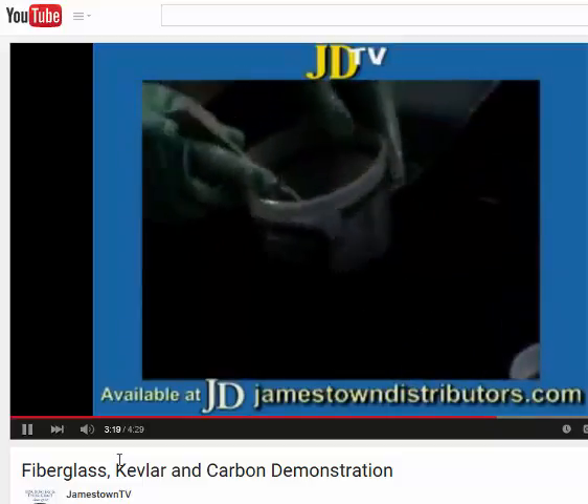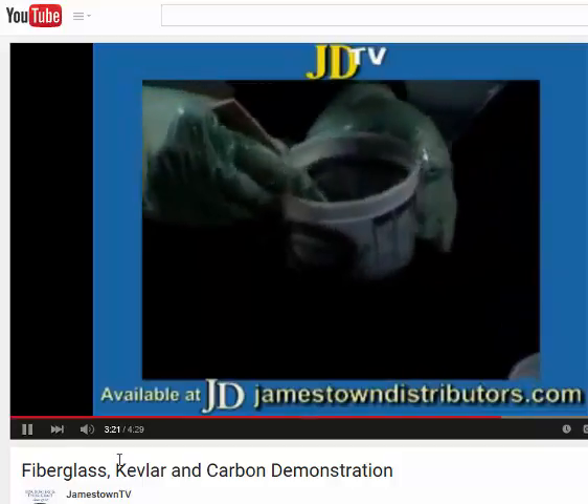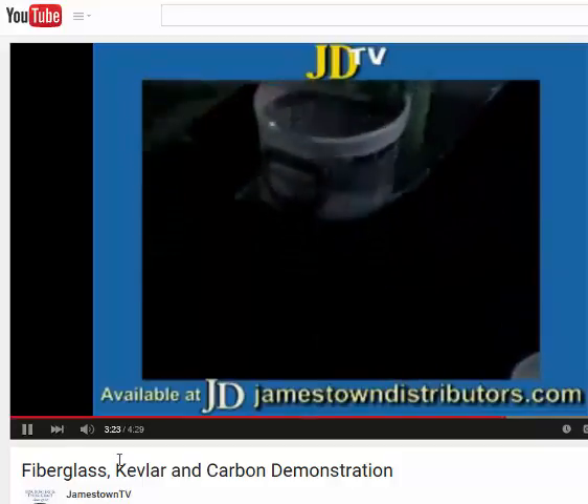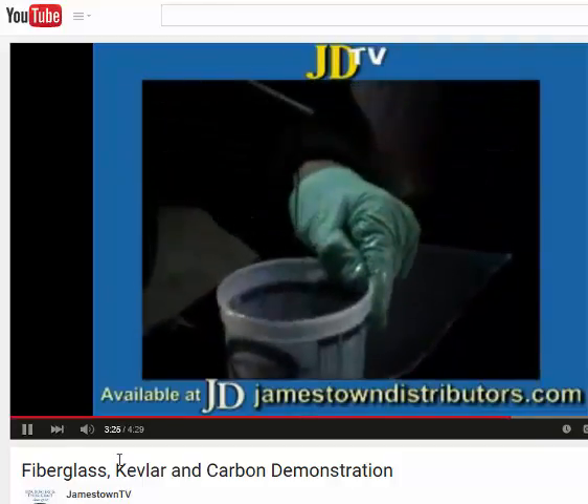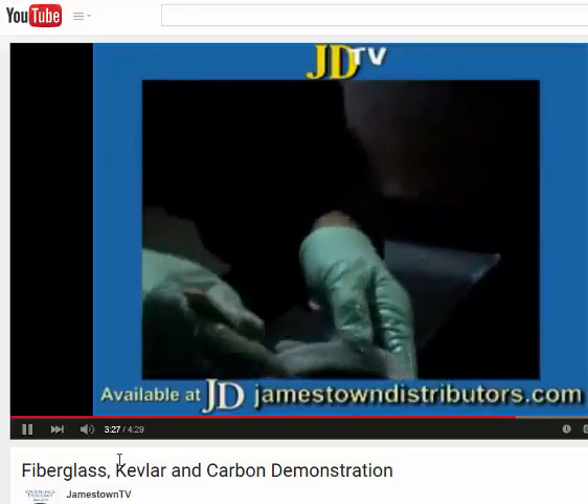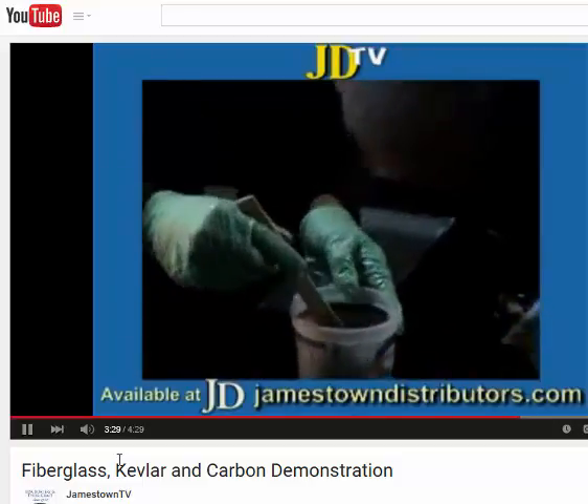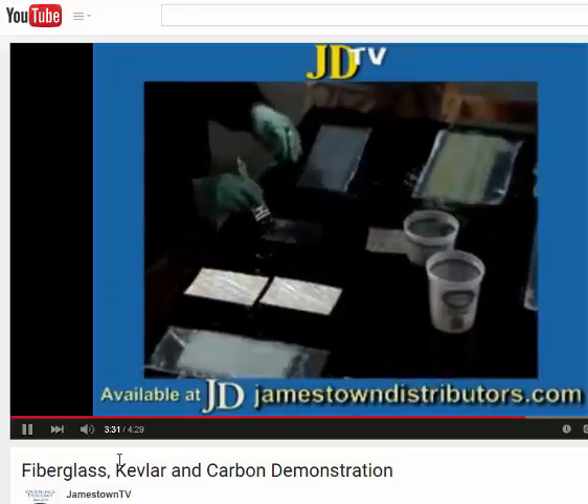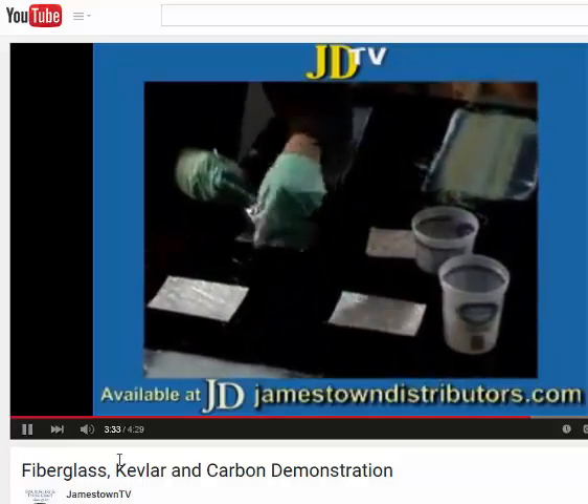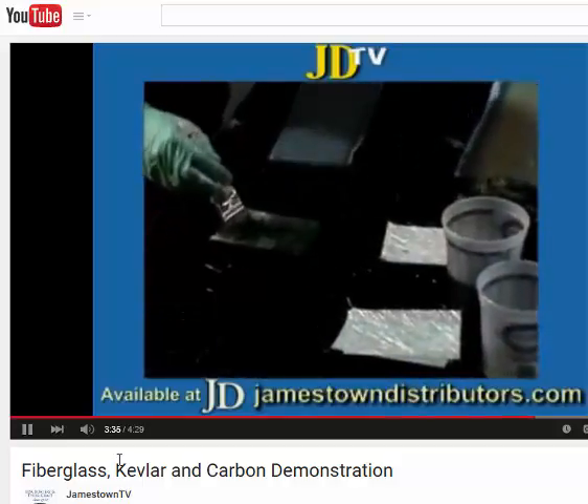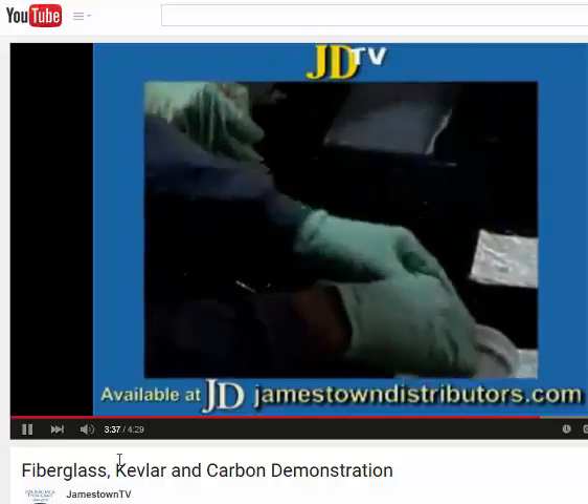This is actually an infusion resin that we have in the shop. It's very, very thin, as you can see, but it's a vinyl ester blend infusion resin. It's a very nice resin. Now, what we could do maybe at the same time is just take the epoxy and do this exact same thing I'm doing with the mat. Just wet that out and then do it side by side.